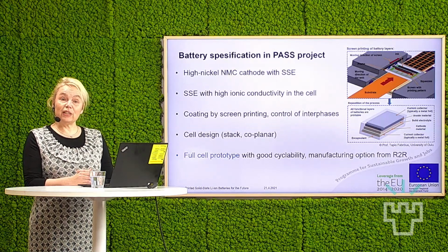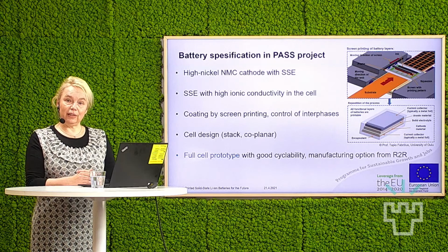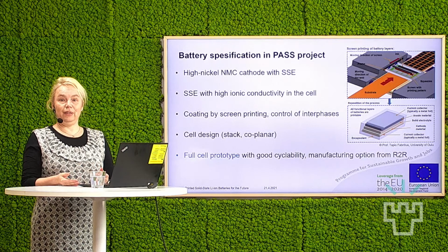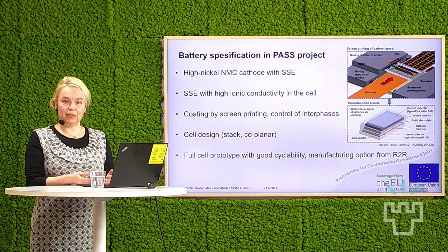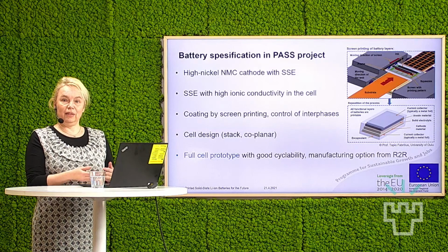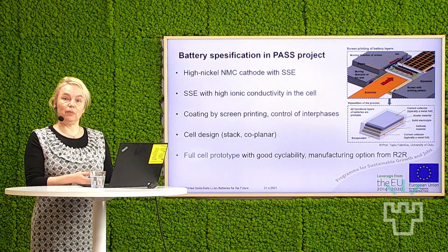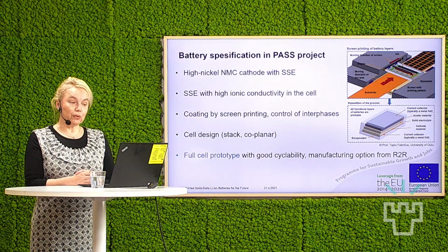One of the key challenges is the solid-state electrolyte, so that we have an electrolyte which has a high ionic conductivity, not only as an electrolyte material, but when it is operating inside the cell. Typically, the operation of the electrolyte inside the cell is not the same as what we measure, for example, as the conductivity of the electrolyte material itself.